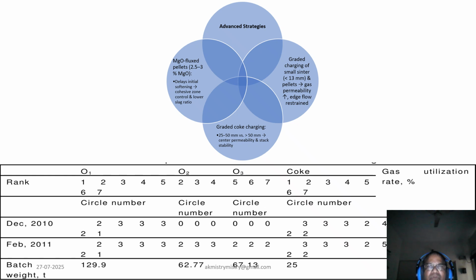So now coming to the advanced cost reduction strategy. To push efficiency further, charging a smaller sinter fraction, less than 13 mm, alongside pellet to boost permeability and limit channeling is also a key. Sort coke by size, 25 to 50 mm versus more than 50 mm, to stabilize the stack interior helps a lot. Introduce MgO enhanced pellet, around 2.5 to 3% MgO, to delay softening and sharpen the cohesive zone, reducing slag volume, which is also paying back a lot of fruitful dividends.